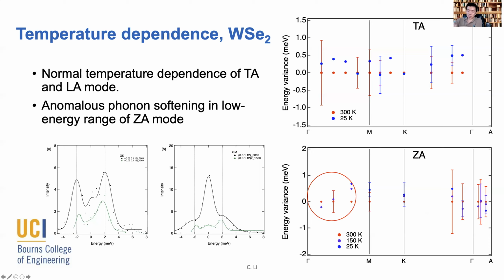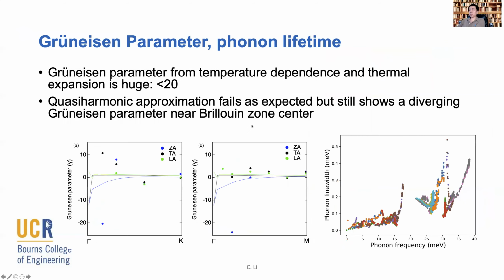So what I'm saying here is the phonon becomes more covalent-like, or the van der Waals interaction becomes more covalent-like between the layers for the flexure mode when the temperature is higher. And when it's colder, it's pushing closer to the quantum limit, where the mode becomes more van der Waals-like bonded. Okay, so if we try to extrapolate to the Grüneisen parameter using the thermal expansion of the material,